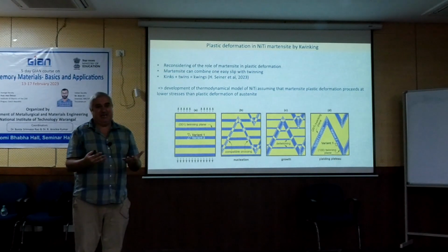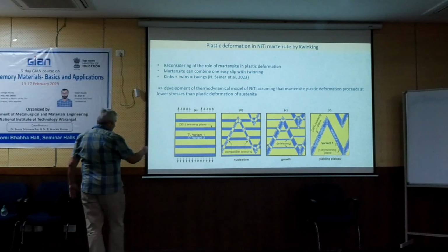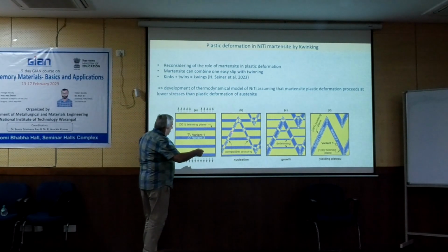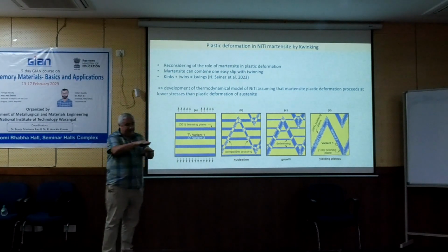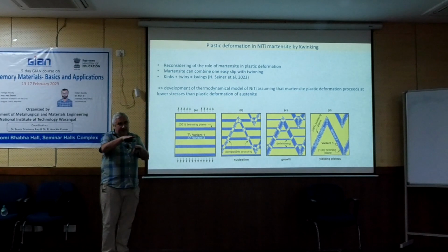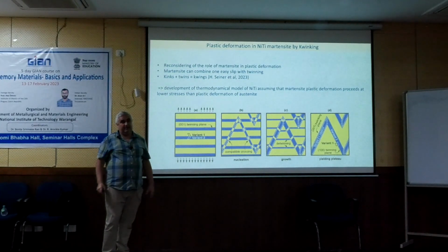It's a dislocation mechanism, only here inside these bands you have a coordinated dislocation slip. Coordinated means that in order to create a homogeneous shear in this stack of papers, you have to glide on every plane some shear. So in this way you get the kink band.